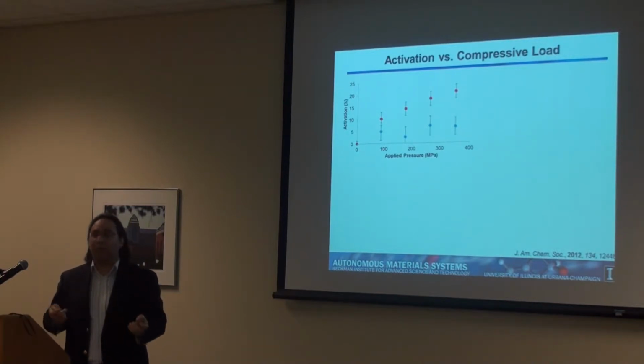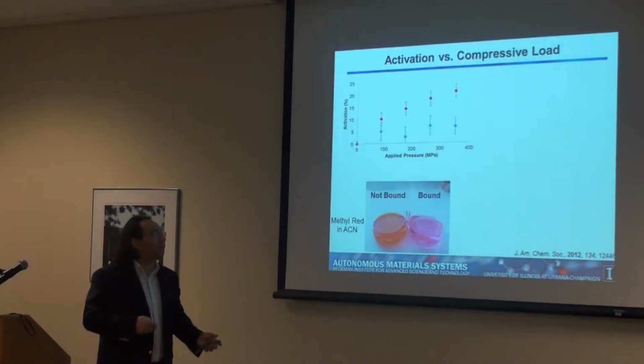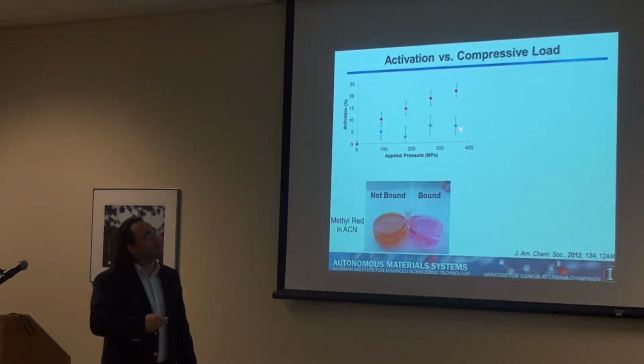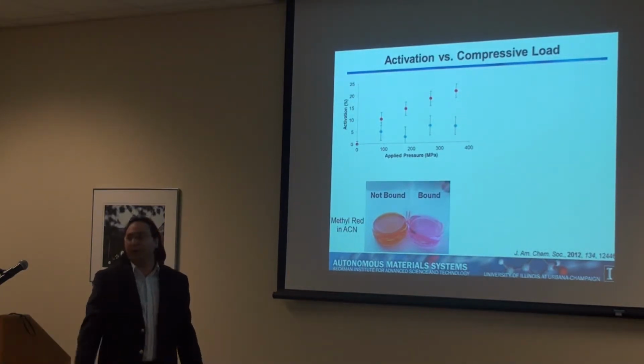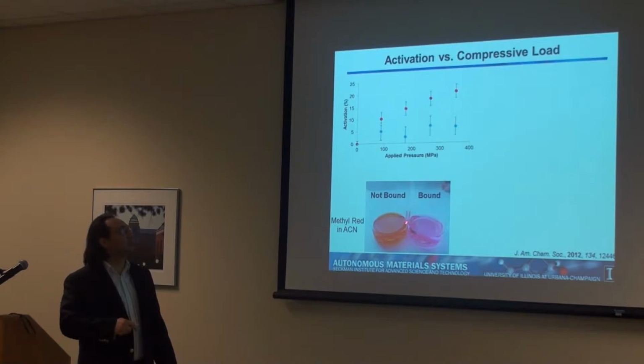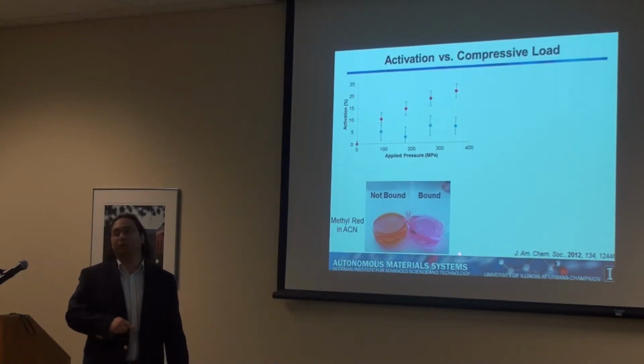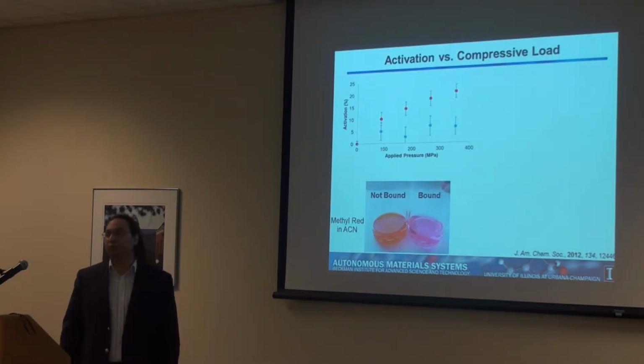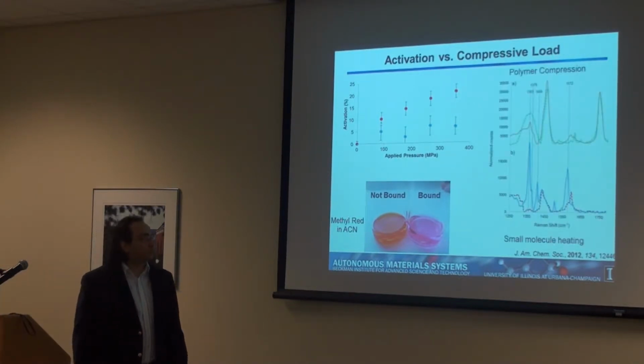It's reacting, but am I producing acid? So for that, it's very simple. I just take these 2 polymers and I add some pH indicator. And in this case, the pH indicator changes color to indicate there is acid in there. This one doesn't show any acid.